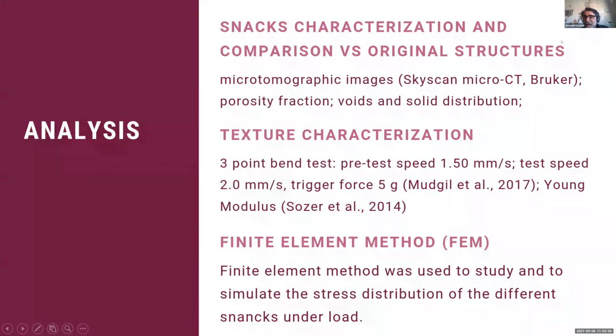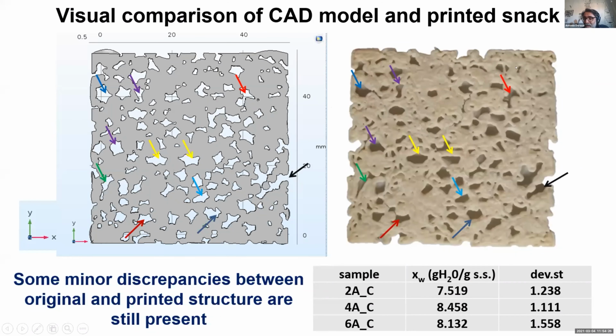These are, in general, the analyses that we performed: microtomographic image, texture characterization with a 3-point bend test. And we also used really popular finite element methods to simulate the stress distribution on the different snacks. So we can see the structure of the snack after cooking. This is not raw material, but after cooking. And we can see that more or less the most important pores are respected. Obviously not in shape, because after cooking, some shape may change a bit.